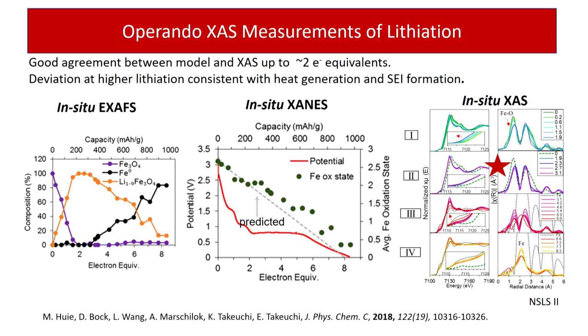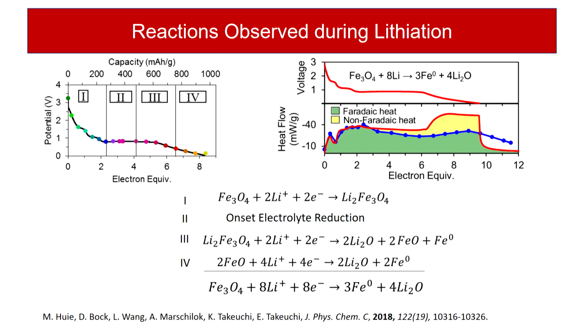The battery keeps discharging, but the iron oxidation state isn't changing. After a while, it begins to change again, but the iron oxidation state remains too high relative to theory. What we're able to establish is that about 2 electrons is the onset of electrolyte reduction. That's where the solid electrolyte interphase begins to form, where instead of reducing the iron centers, we're in fact reducing the electrolyte, forming a film on the surface of the magnetite electrode. And then after we reduce sufficient electrolyte, the iron reduction continues to form iron metal. Control of that interface is critical to the reversibility of the system.